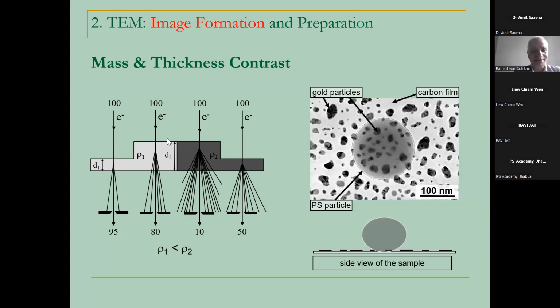And in this case, if we allow the electrons to pass through the same thickness, but with much higher density, then the electrons will be much more scattered, and the electrons reaching the other part unhindered will be much less. Whereas if the density is lower, then as expected, the number of electrons scattered will be low. So exactly this effect will be analyzed in forming the images in transmission electron micrographs.